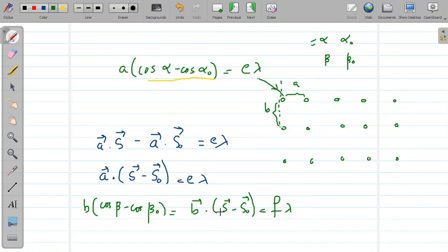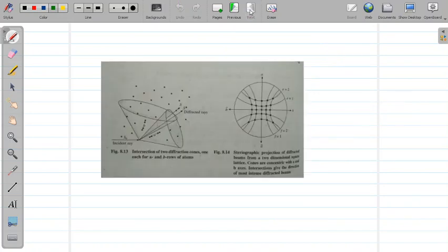So this also means that the incident ray can diffract along another direction, making an angle beta, and this equation also gives the possibility of formation of cones along the diffracted direction. So I will show you a picture. Here you can see this is the incident ray, and you can see a two-dimensional arrangement of atoms here. All the dots represent the atoms. It is a two-dimensional arrangement, and this direction is the first dimension. This is the A bar row of atoms. And the second dimension is this. This is the B bar row of atoms.